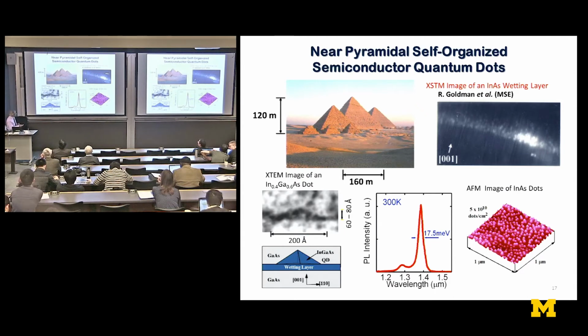And here's some very important work. This settled it once and for all, that yes, you do have a wetting layer. It's a Stranski-Krastanov growth mode, and the quantum dot is kind of immersed in that wetting layer. And this had tremendous ramifications in understanding the carrier dynamics and all kinds of things going on, as I'll come to later. And here's the photoluminescence of these dots, very narrow line widths in spite of the size distribution and all that. And here's the luminescence from the wetting layer.